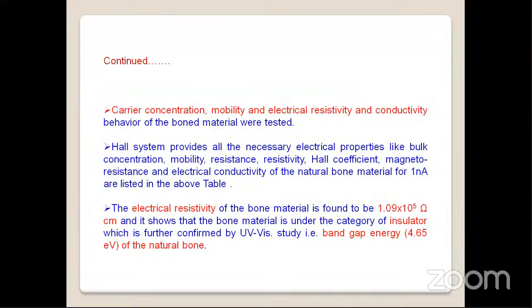Then carrier concentration, mobility, electric resistivity, so many parameters one can identify, like mobility, resistance, resistivity, Hall coefficient, magnetoresistance, and all. But the important point which I am going to correlate with the UV visible spectroscopy is that it shows an electrical resistivity of about 1.09 × 10^5 ohm. That is very huge. This is in the range of the insulating material category. So this insulating behavior of the prepared materials is confirmed by both studies: the UV visible spectroscopy band gap value and the electrical resistivity value from Hall.